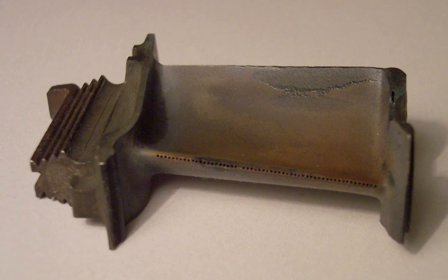The MCrAlY is the latest generation of bond coat and does not strongly interact with the substrate, normally applied by plasma spraying. MCrAlY coatings are secondary aluminum oxide formers. This means that the coatings form an outer layer of chromium oxide, chromia, and a secondary aluminum oxide, alumina, layer underneath. These oxide formations occur at high temperatures in the range of those that superalloys usually encounter. The chromia provides oxidation and hot corrosion resistance. The alumina controls oxidation mechanisms by limiting oxide growth by self-passivating.